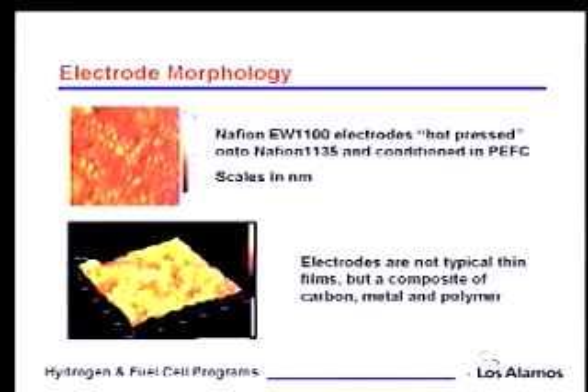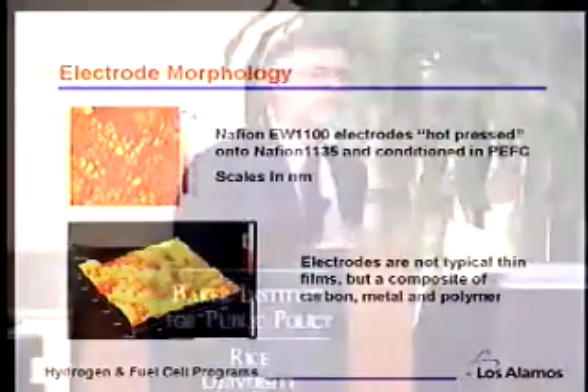The scale on each of these at the high end is about 800 nanometers. So we're looking at an electrode that's about a micron thick, and these lumps, these particles you see here are on the order of 600 or 700 nanometers. We call these thin film electrodes, but they're really composites, and they're composites of carbon, metal, and polymer.